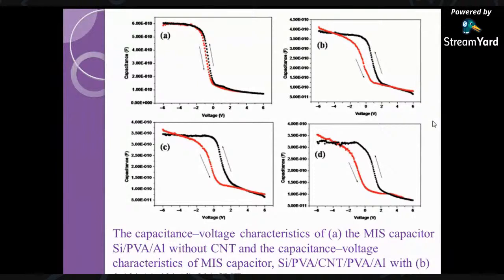When talking about the application point of view, carbon nanotubes are a good candidate for memory devices. So here you can see the characterization of memory devices, which is a capacitance voltage study for a material with different doping of carbon nanotubes. You can see this window, the potential window, increasing with the increase of the content of carbon nanotubes in the device. So it gives information that the carbon nanotubes have the capacity to store more charge, and they can store more data. So maybe 1% loading of carbon nanotubes gives the maximum storage without any leakage of current.